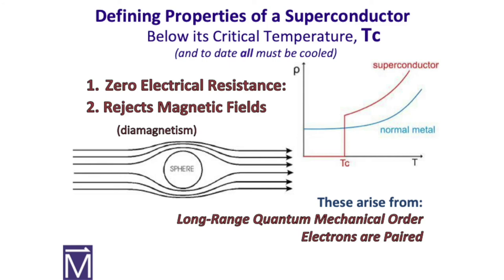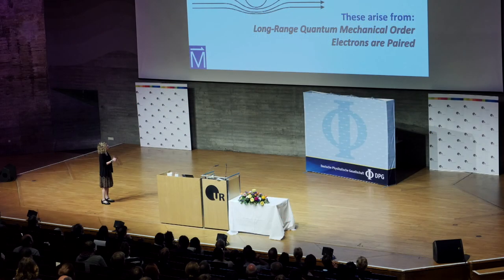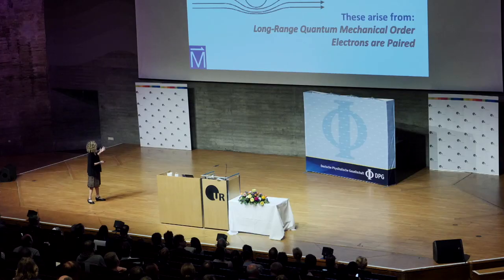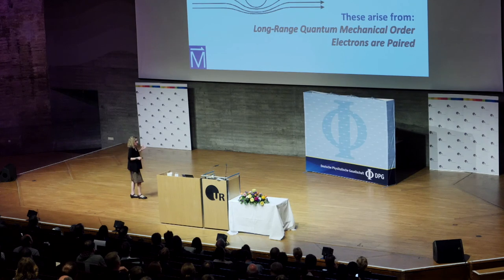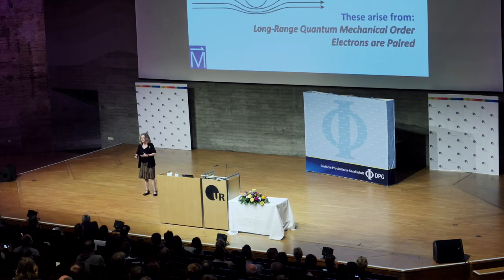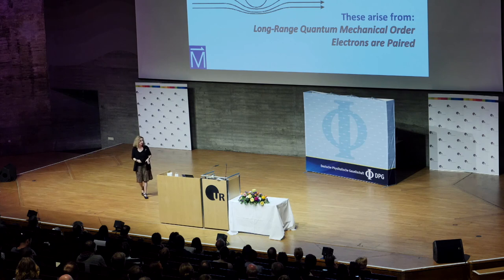I think most of you know that a superconductor has a resistivity that decreases with decreasing temperature. And unlike a normal metal, below a certain temperature, the resistivity falls to zero, typically very, very quickly. And this, in conventional superconductors, is a solved problem. I'll argue that several times here. But another thing that happens in superconductors, which was a big giveaway to the mechanism, is that they expel magnetic fields. Conventional superconductors abhor magnetic fields. They just spit those magnetic field lines out.